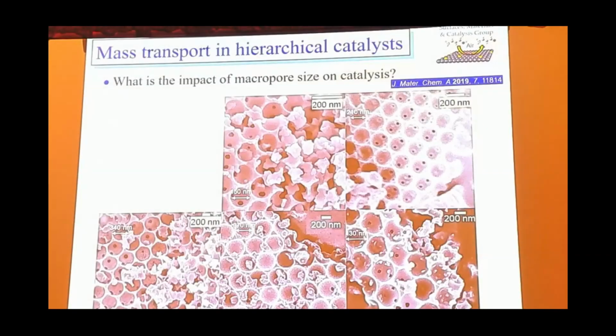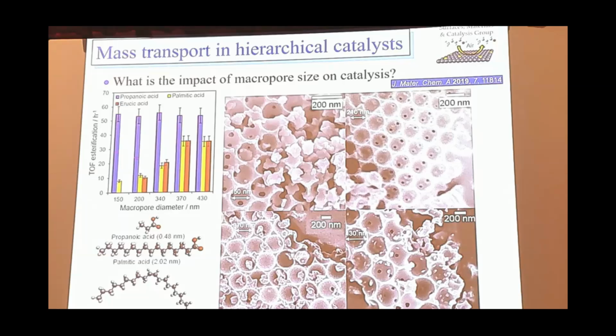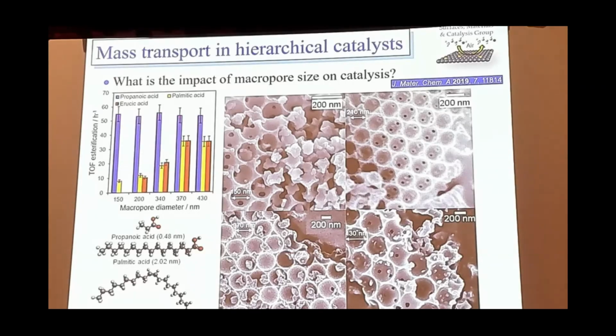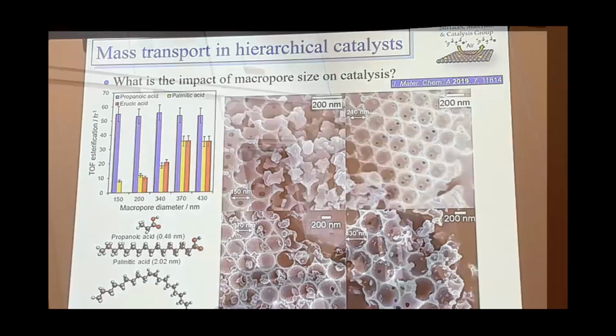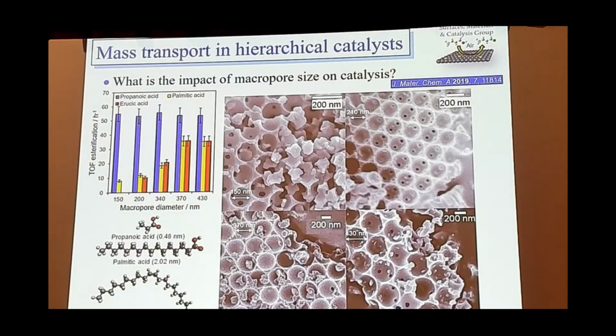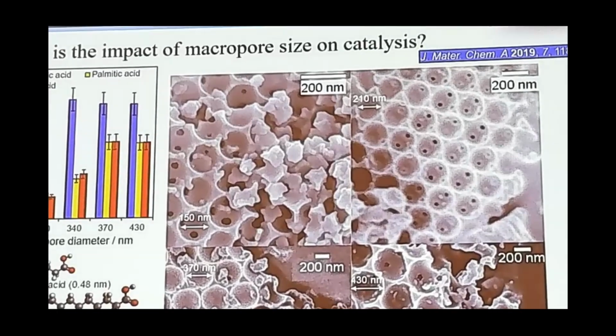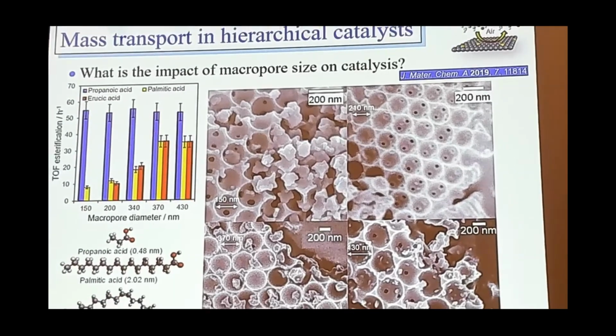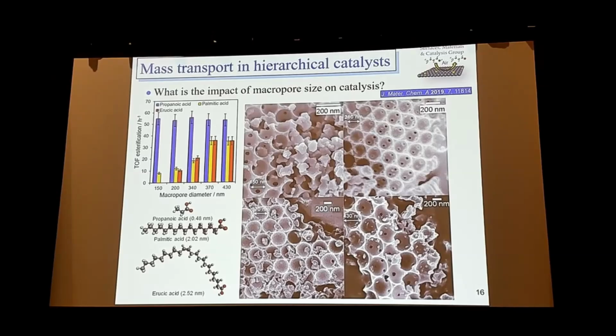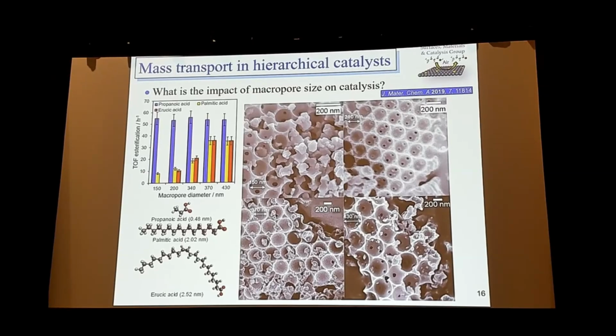And we've been able to demonstrate this using relaxation NMR with our collaborators at the University of Western Australia. But we can actually see with the catalysis the impact of that, of course. If we look at esterification of different chain length fatty acids, so in blue, short chain acid C3, it can diffuse anywhere. If you look at the longer chains like palmitic and erucic acid, and you've got various pores, the rate is quite low. You increase the size of the macropores, the diffusion gets improved, and then you increase the rate of reaction. So here, these will all be functionalized with the same active site. We have sulfonic acids on these. So the turnover frequency should be the same per active site. So the only reason we're seeing a difference in turnover frequency is because the majority of the acid sites are not accessible when you've got diffusion limitation.